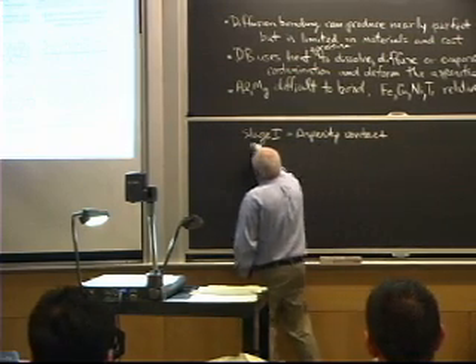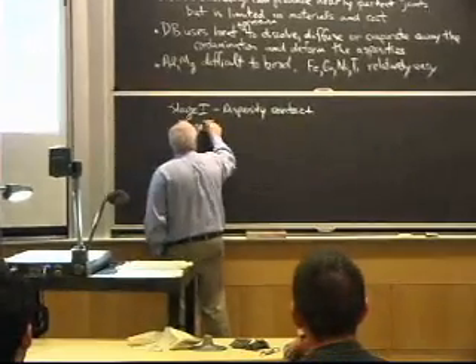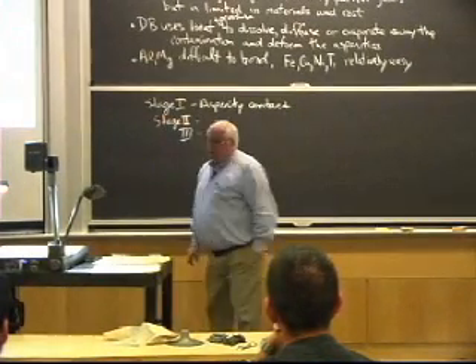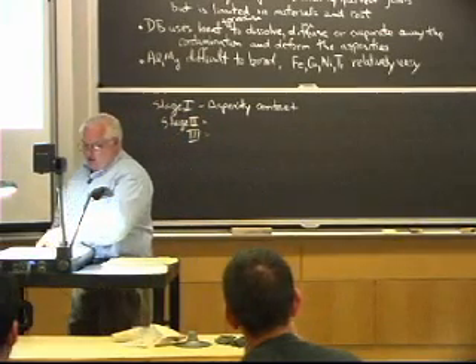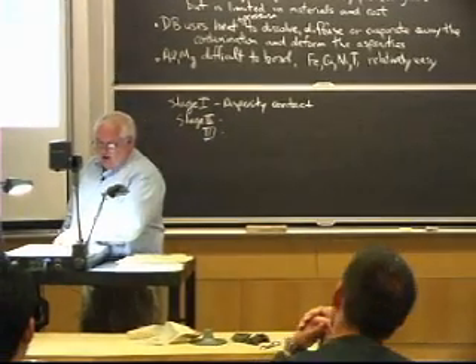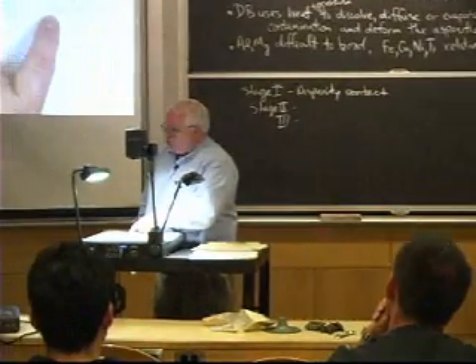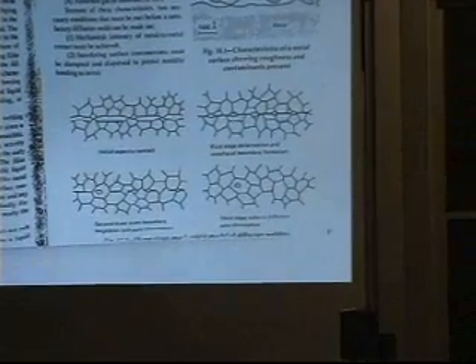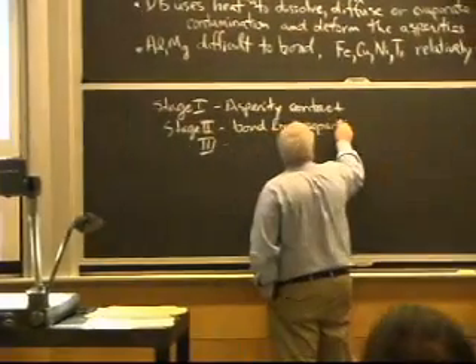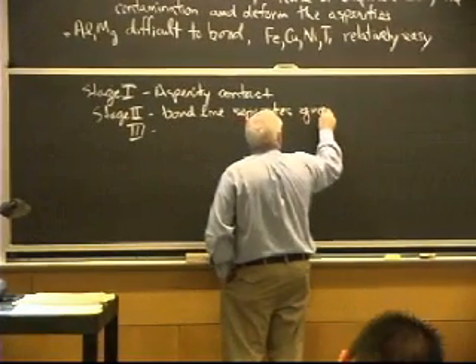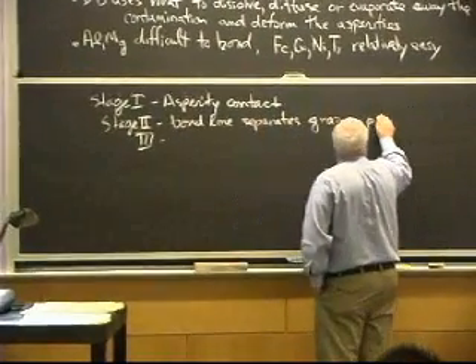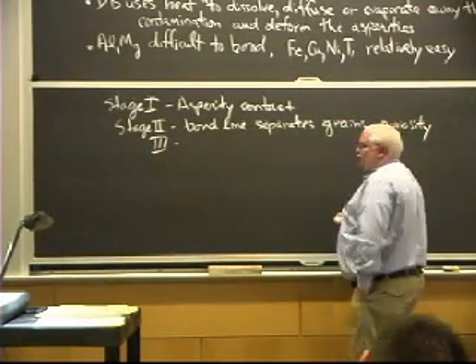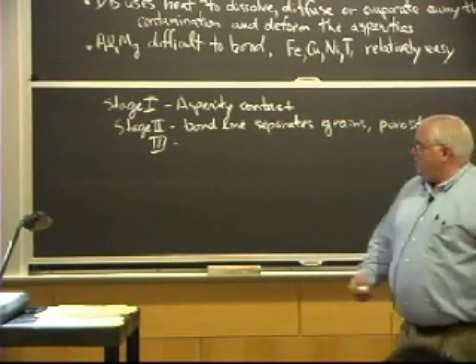And the next one is cleverly stage 2. And then we have stage 3. So the first one's asperity contact. The second one is basically where the diffusion starts to take place, and I still have separate grains on either side, but this heavier black line is basically showing you where the bond line is, and then you have pores in here. So you have the bond line that separates grains in the metal, and you have porosity. So you've got a perforated grain boundary as your interface, and that's not a full bond.